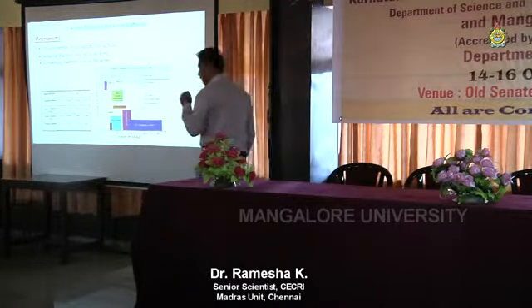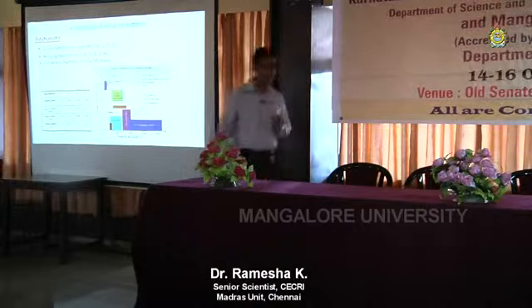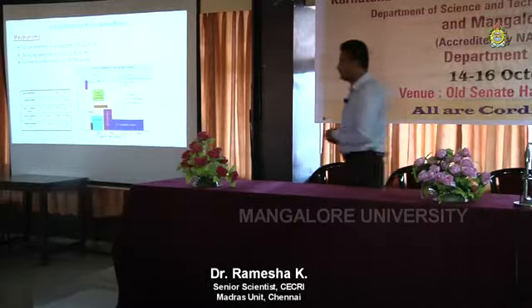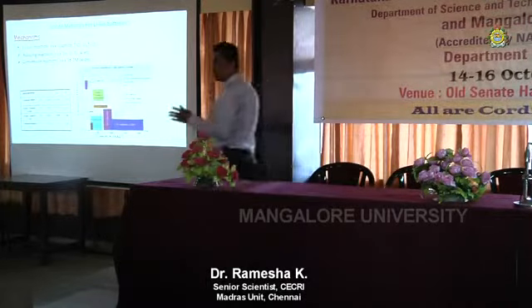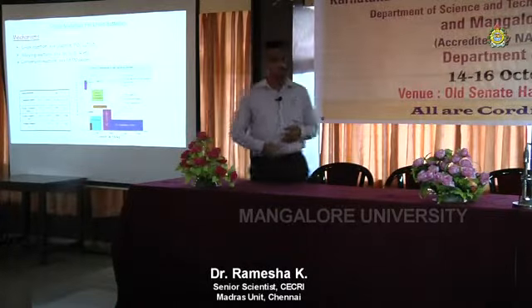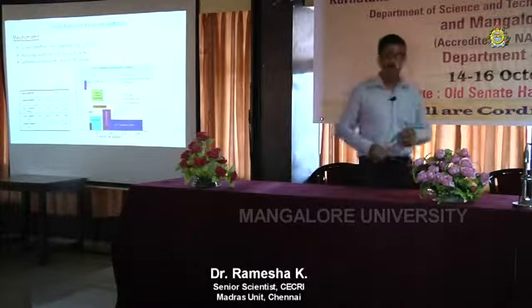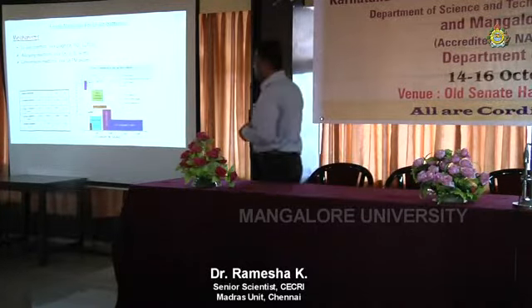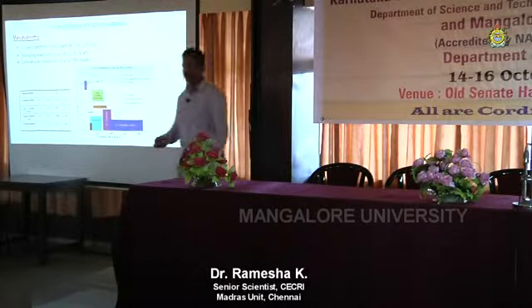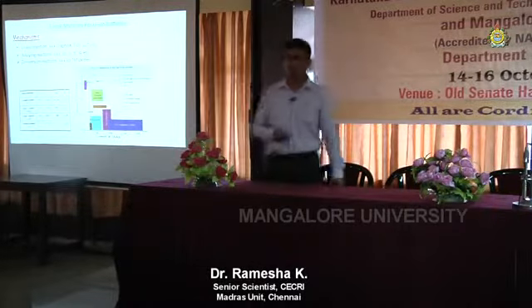That means about 3 times volume change of that particle. Now you make a battery with silicon or tin, and during the lithium reaction the electrode bulges with 300% volume change, that means 3 times. So your battery has to give the alloy that much volume. That is the real problem with the alloying reaction. Even though silicon, bismuth, and tin all look about 10 times better than graphite, the problem is the volume change. How do you accommodate it?